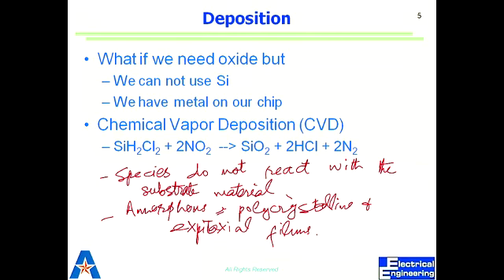When we do this deposition, essentially we are not reacting the material at the top, we are depositing. For oxidation, if you see the word growth, that means thermal oxidation where you are consuming silicon. But if you talk about oxide deposition, we'll be talking about one of these methods, CVD or PVD. Right. What is PVD? Physical vapor deposition. And what is CVD? Chemical. So both differ in nature. In one case, there's a chemical reaction that results in the resultant species being deposited. In another case, we have a solid material, we heat it up, we make vapors out of it, and we deposit those vapors. We heat it up maybe by just applying heat or by using an e-beam to melt it.